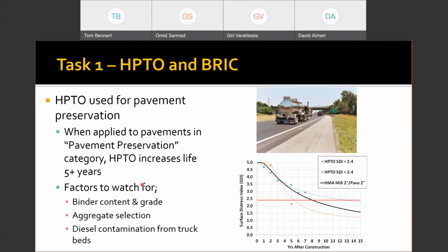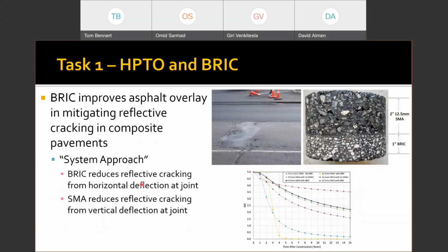So we're finding that, again, in this sort of practice, as long as we're putting them on sound pavements, obviously, you put it on garbage, you're going to get garbage, but if we put them on sound pavements, they're going to perform rather well. We've done similar work with our other materials, such as bituminous-rich intermediate course and SMA. And for those of you that may not be aware, New Jersey, although it looks like we traditionally have mostly asphalt pavements in the state, over 60% of the network that's owned and operated by New Jersey DOT is what we call composite. And that is an old concrete pavement with asphalt on the surface. That presents a very significant challenge for designing because of the movement around the joints and the cracks.